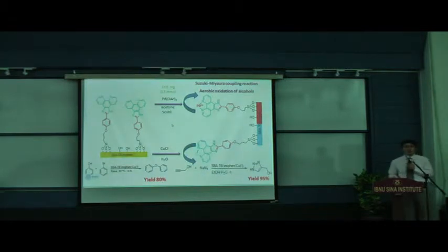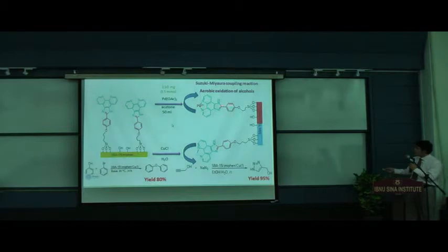So based on this finding, we also played with other ligands. Phenanthroline, we know that is a very good ligand for too many metal ions, especially for iron. We also studied palladium complexation with this phenanthroline at the surface of SBA-15, and also complexation of copper with this moiety at the surface of silica, and each one was used as Suzuki-Miyaura coupling reaction catalyst and aerobic oxidation of alcohol catalyst, and in the case of copper, we used it for Ullmann coupling and click chemistry. Look at the yields, almost high and excellent.